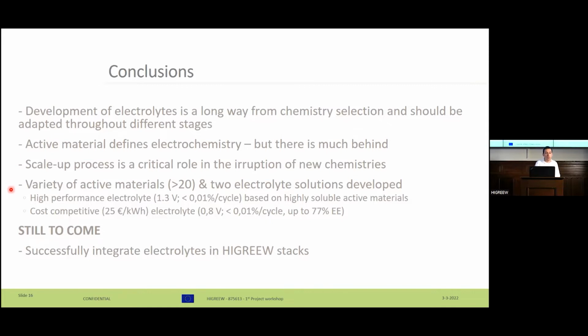So a more scientific conclusion is that we managed to have a total of more than 20 active materials, and that we define 2 different electrolyte solutions. As I mentioned, one of those would be a high performance electrolyte with up to 1.3 volts, with a capacity decay lower than 0.01% per cycle, and based on highly soluble active materials that potentially can get to high energy density. In comparison, we have a cost-competitive solution based on viologen and ferrocyanide, which has a lower cell voltage, but still a high capacity retention, and with some tuning we managed to get high energy efficiencies, which is really valuable for working at neutral pH.